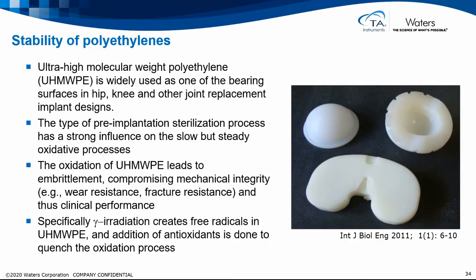Ultra-high molecular weight polyethylene is widely used as one of the bearing surfaces in joint replacements. It's known that the pre-implantation sterilization process has a strong influence on slow but steady oxidative processes, and this will lead to embrittlement and compromising the mechanical integrity and thus the clinical performance. Specifically, gamma irradiated material creates free radicals in the material, and addition of antioxidants such as alpha tocopherol is done to quench this oxidation process.